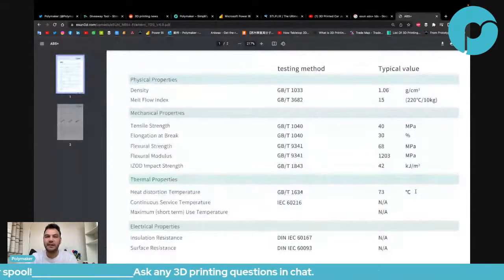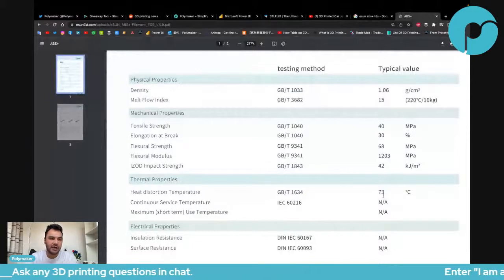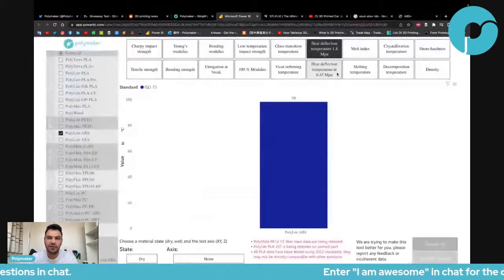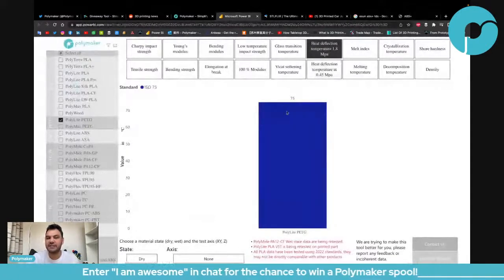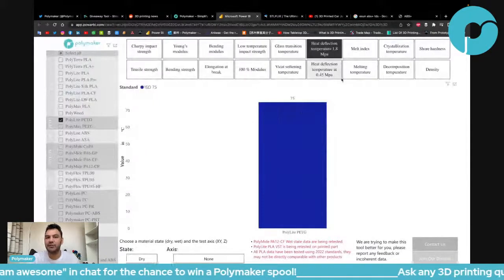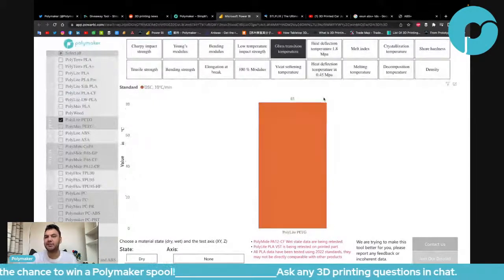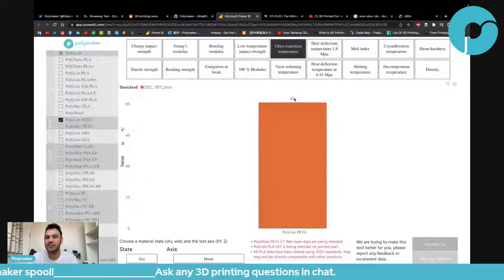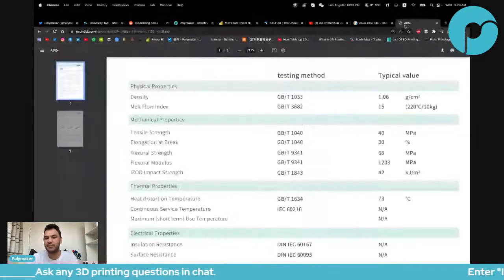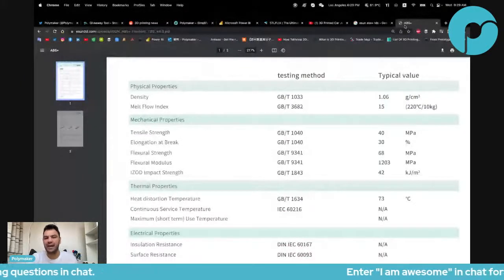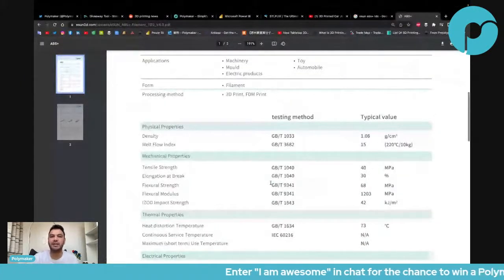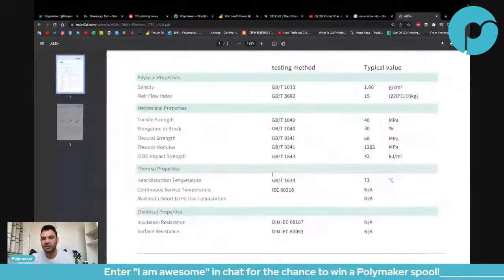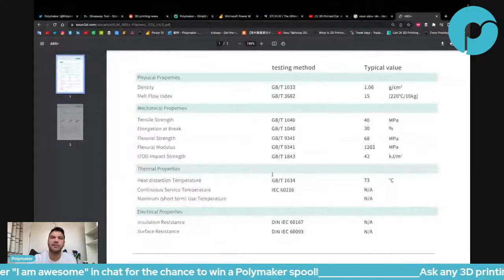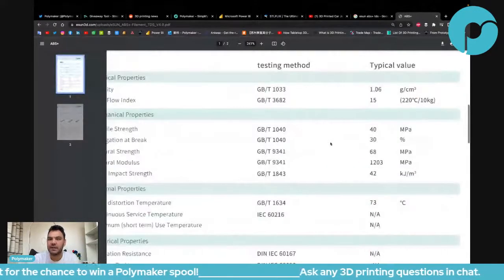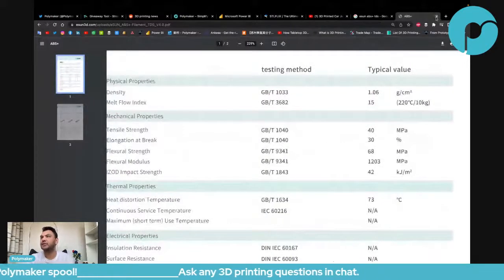And then if you compare it with PETG, for example our PolyLite PETG, you see the HDT of our PolyLite PETG, even the HDT at 1.8 megapascal, is 75. So even our PETG, the Tg is 81. So even our PETG is more heat resistant than their ABS Plus. That's what I highlighted, because a lot of people were talking about ABS Plus, and I felt like the difference between ABS and ABS Plus was not clear in their mind. So that's why we did some research during one of the past streams. Yeah, so hopefully that answers your question.